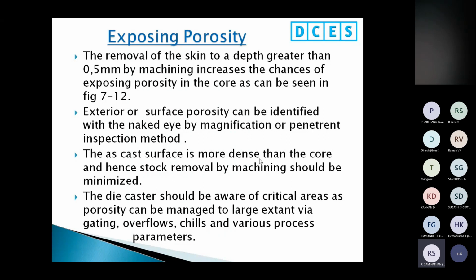The die caster should be aware of critical areas, as porosity can be managed to a large extent via gating, overflow, chill, and various process parameters. So the porosity standard should be taken care of during the die design, by a proper gating system, properly allocated overflow in the casting gating system, and chill vents.